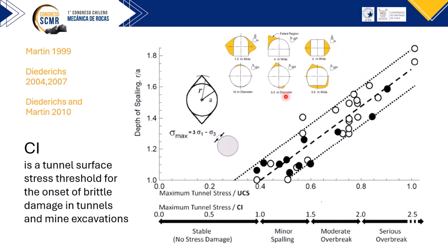These are a bunch of case studies that were done in the 90s out of the GRC in Laurentian, but the case studies are international. These are cases where people went in where rock had failed and excavated everything they could excavate back to the truly intact rock. So this is kind of a maximum damage, and you can see that it begins at about 40% of the UCS, but more importantly, it begins at CI for most rock masses. So this is empirical evidence, and you can track the damage.